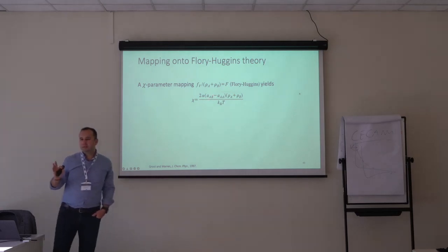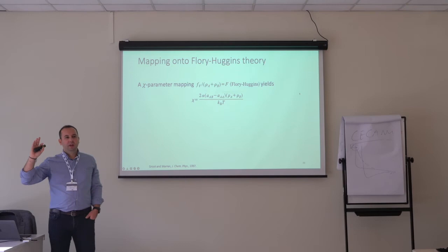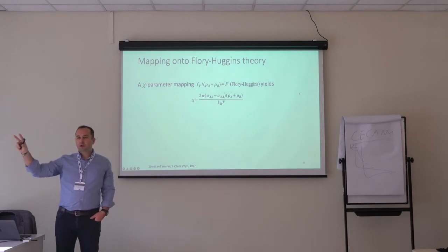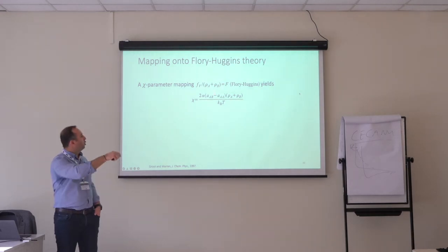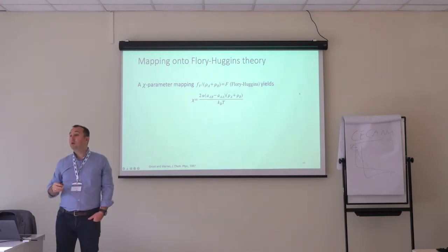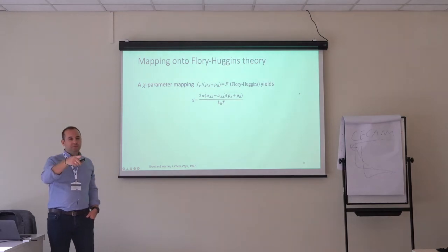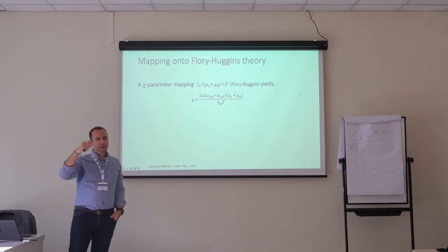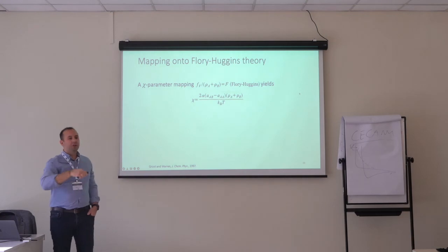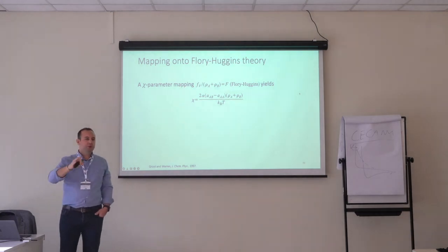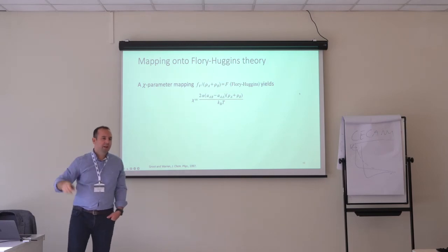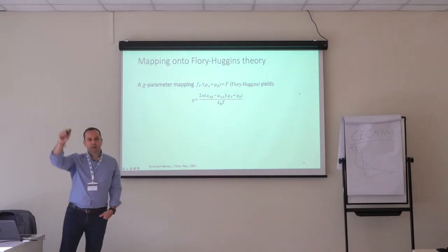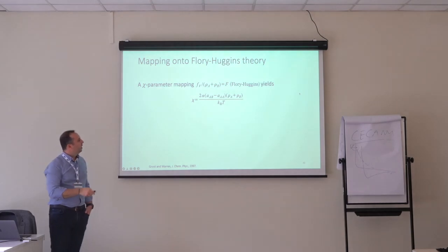That is really nice because now you can make your coarse-grained beads, estimate the chi parameter from experiments, and then compute your DPD non-bonded interaction strength. You asked in the previous session about bonded and non-bonded, so this is only for the non-bonded. For bonded interactions, you still use the spring potential. That is the same, and for the angle that is there. But this is for the non-bonded interactions.